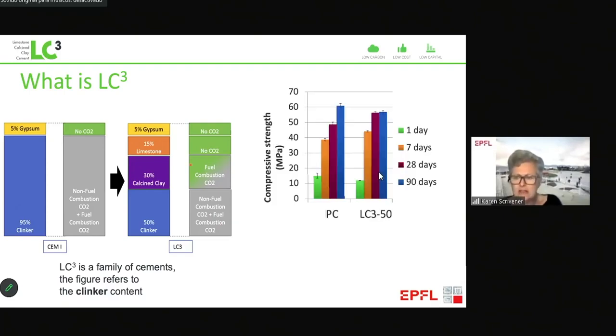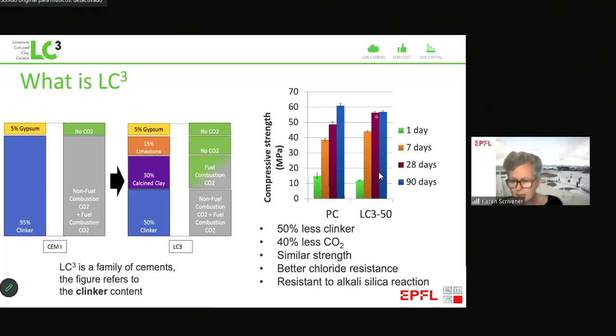But what's really interesting is even though you've got these very high levels of substitution, and this is unlike most other pozzolanic materials, you get the same or better strength. So we have slightly lower strength maybe at 1 day, but we have higher strength already at 7 days. And in fact, even in this example here, the strength was slightly lower at 1 day. If you have good grinding technologies, you can even meet the same strength at 1 day. And this cannot be done with other substitute materials. And at 7 and 28 days, this is higher.